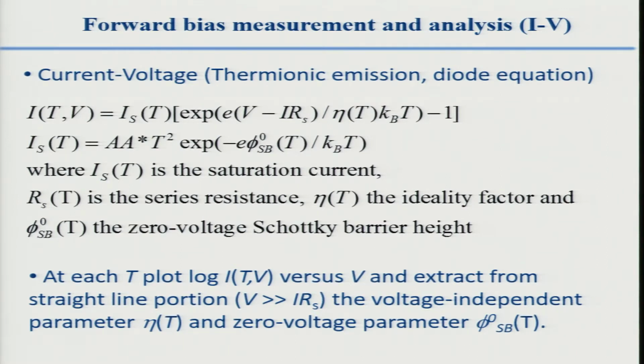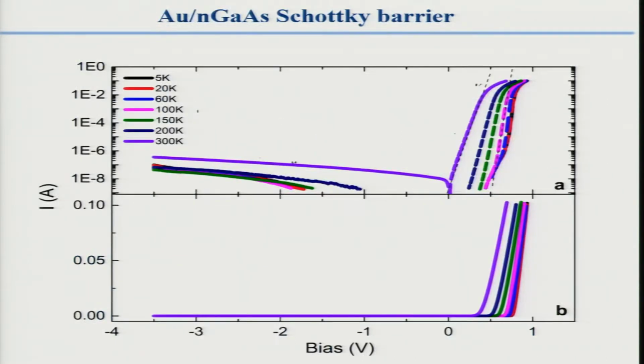We extract these parameters from data like this. This is a gold N-type gallium arsenide Schottky barrier at different temperatures, the low temperatures being over to the right. This is linear. This is log linear. And we have forward bias, reverse bias around 0 here. So around 0.6 of a volt, you get all the conduction you want.